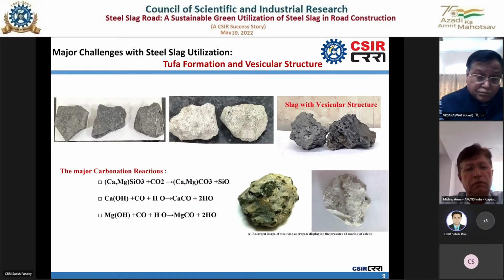The second important challenge is tufa formation, since steel slag aggregate normally contains a high amount of calcium oxide, between 45 to 54%. And this calcium oxide, by virtue of the carbonation process, forms calcite deposits on the surface, which can impede the drainage characteristic of the pavement layer. So by altering the slag cooling methodology, as well as by modifying the weathering process, we can reduce this tufa formation in the steel slag aggregate.